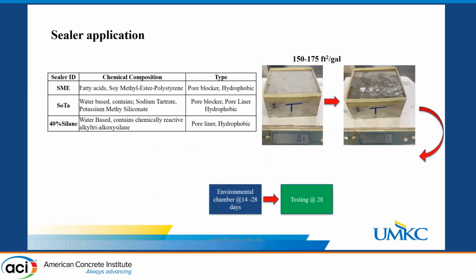After that, the sealers we used in this research all have a mode of action of hydrophobicity, which is another word for water repellent, and they try to stop water ingress into concrete. The first one we call soy methyl ester, the second one sodium tartrate, and the third one is a 40% silane. We cannot mention the product names because of US rules. The first sealer is a pore blocker, the second is a partial pore blocker and pore liner at the same time, and the third is a pore liner.